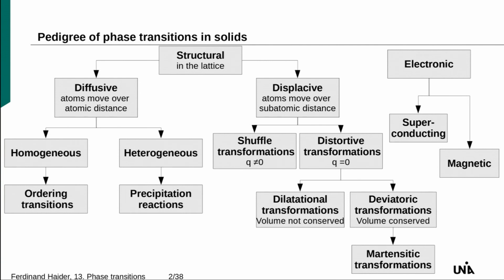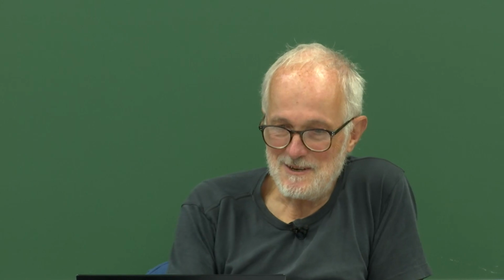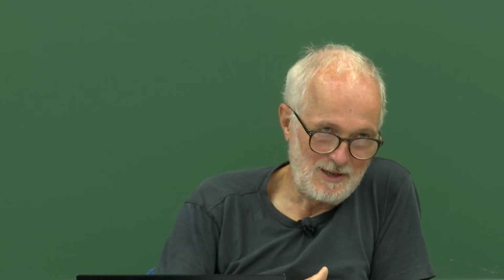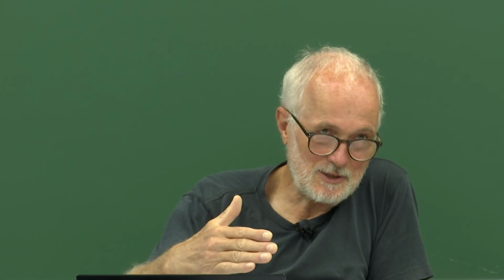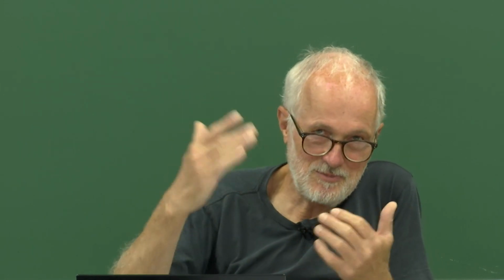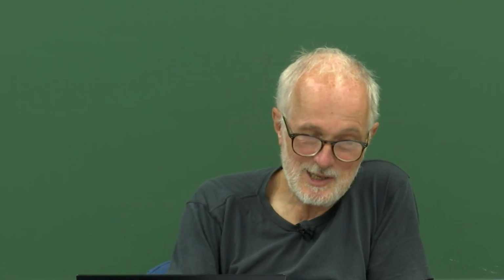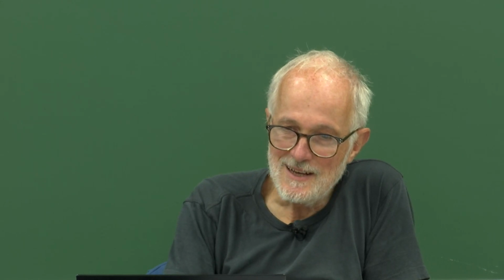Coming back to our lecture, these displacive transformations can be nicely studied using molecular dynamics, because they take place usually pretty fast and don't require very large systems. It just has slight displacements. Very often they proceed with the velocity of sound in the system, so several thousand meters per second. That's why, for a system of say 10 to 50 nanometer size, the time scale required is sufficient to cover in MD.